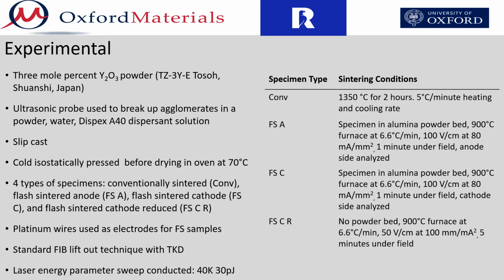2 specimens came from opposing sides of the same green body specimen, one from the anode and one from the cathode. Finally, a 4th specimen subjected to a higher current for a longer timescale was sectioned, and the cathode was analyzed to study the effect of a stronger electrochemically reducing environment on microstructural chemistry.